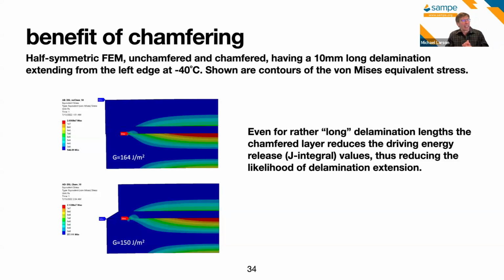We did some modeling with this, and just because we are enamored with this idea of changing the geometry in order to try to preserve our specimen, here's an example of having a 10 millimeter long failure in a specimen that you could see is about 40 millimeters tall in a layer that picks up a PSA adhesive. Just having that chamfer out there lowered the driving energy release rate significantly. So again, if you have some initial flaw in your adhesive layer, it happens to be at the edge where you have the stress concentrations, you can reduce the driving force with a geometry change solution that will help. So that is, again, something to keep in mind rather than always just to search for a better adhesive.